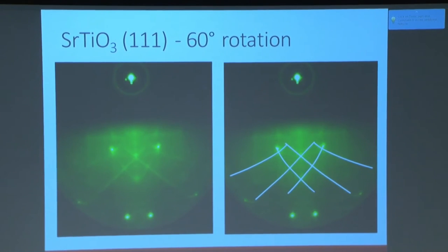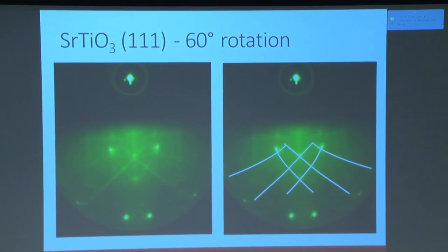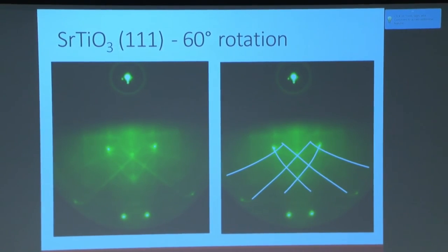Okay, so essentially the straight lines are formed by the elastic scattering that happens on the surface. But one of the variables that defines the luminosity of these vertical lines is also the smoothness of the substrate surface. In this case, our substrate surface was not very smooth, so the vertical lines that we got were not as clear as the ones that I showed in a previous slide. So that also confounds many things, because we need to figure out exactly what the thresholds are for each of the Kikuchi line structures that we have.